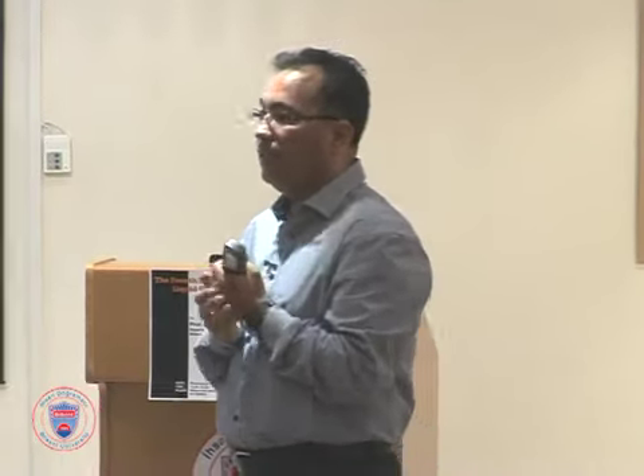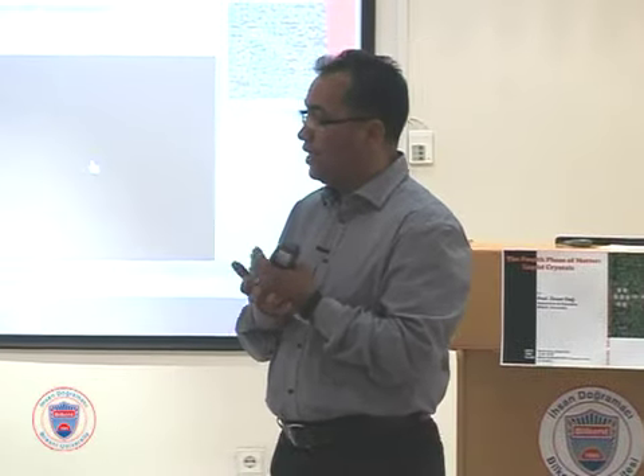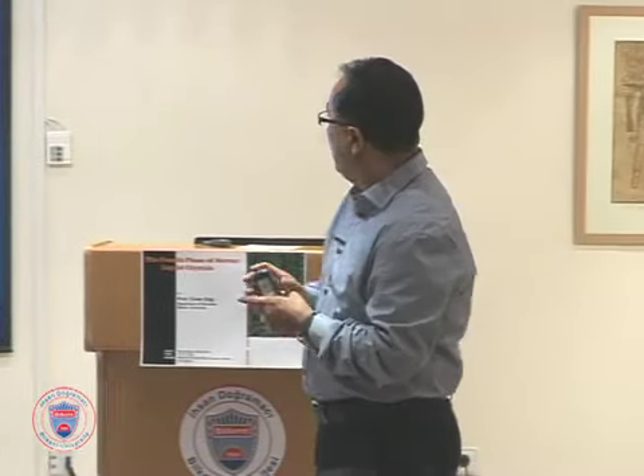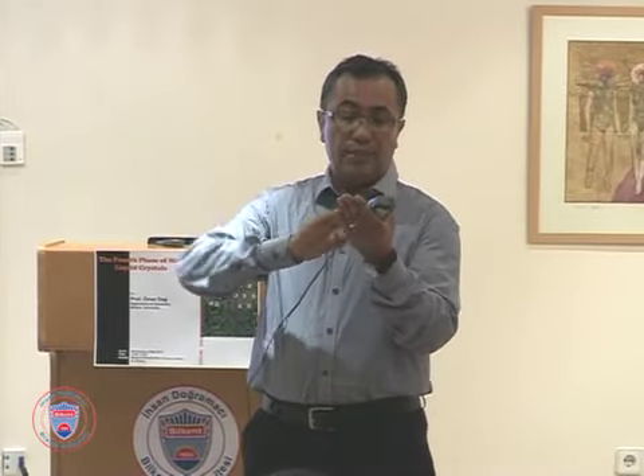You see, the middle region is going from blue to white, blue to white. This is 2 electrodes. I will explain this and I will stop. This is 2 electrodes, 2 glass, basically coated on each surface with a conducting solid material. It is called indium tin oxide, a transparent conductor. And on the surface of this conducting electrode, 2 polymers are coated on each side. And you have to oxidize and reduce this polymer to get color. And to do that, you need electrolyte in between.